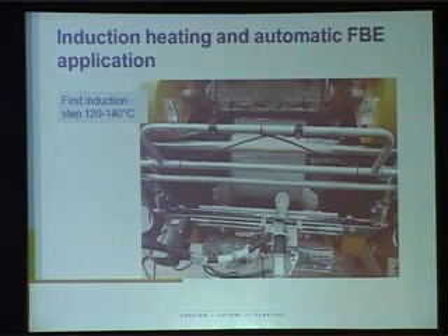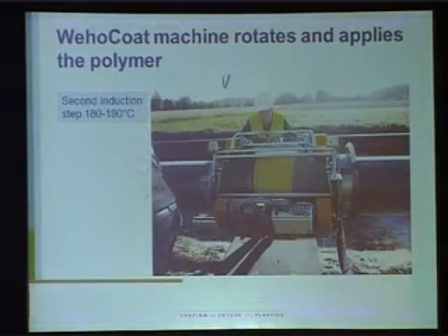In the first rotation, a small induction heating plate heats the surface of the steel substrate to 120 degrees centigrade only, and FBE is applied. Now, low temperature does not allow FBE to cure, but just holds it in place. A set of hot air blowers also heat up the parent coating in the cutback area for proper welding. Now, in the second rotation, it is heated up to 180, 190 degrees centigrade when the epoxy starts curing, and this is when the polyethylene is applied. Being reactive PE, it bonds with the FBE and also it welds with the parent polyethylene, and the peel strength is more than 200 Newton per centimeter, which is far above ISO 21809.